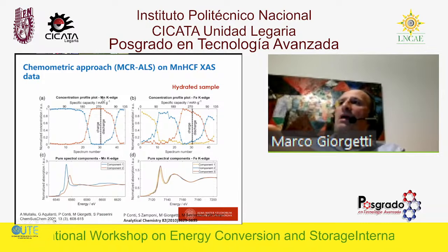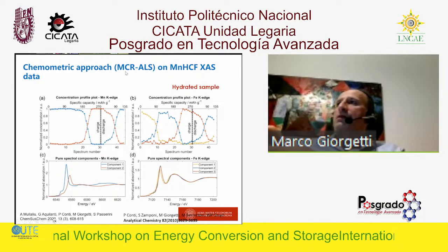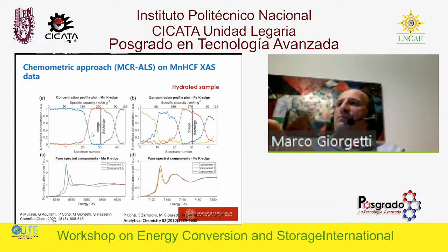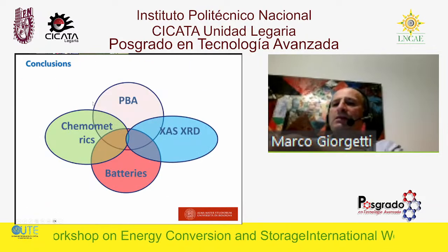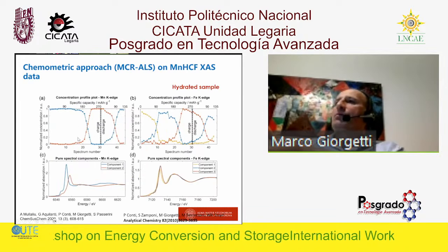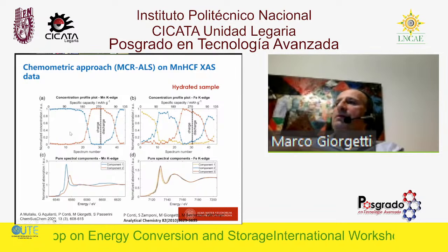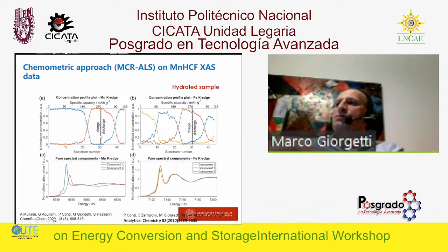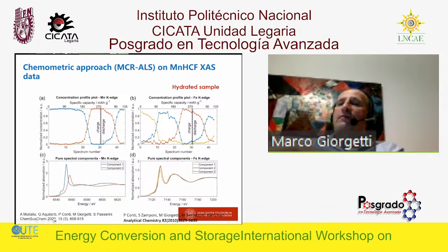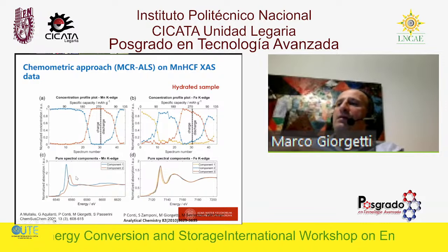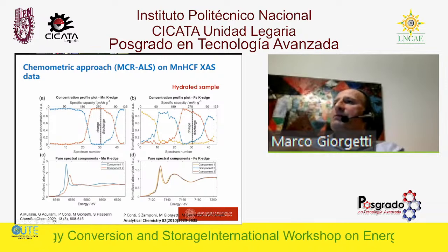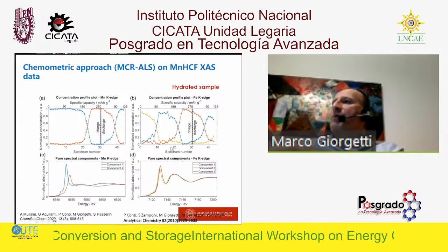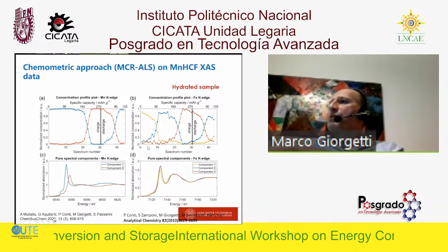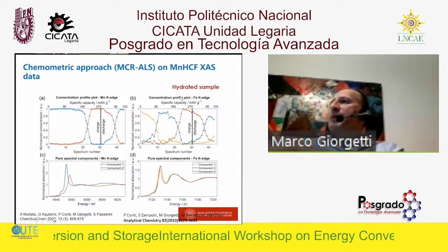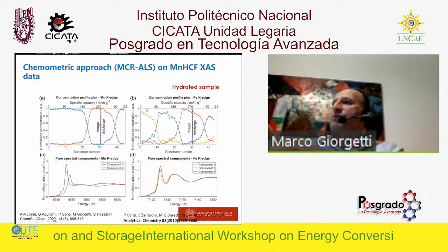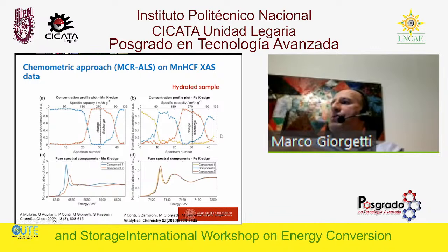This is, for instance, an example that we have on the manganese K-edge and the iron K-edge on the manganese cyanoferrate sample. We can see from this plot that at the beginning we have just the 2 spectra. Then we have a conversion from one species to the other during the charge, and the opposite during the discharge. So we have basically 2 components, one transformed into the other. But what is very interesting is that this is the manganese K-edge. If you see the plot of the iron K-edge, we were able to identify that we also have something popping up here. That was due to the fact that we have hydrated samples. So probably we have a transformation from hydrated to dehydrated, and then we have the charge compensation phenomenon.